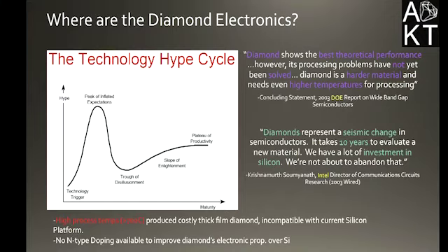Diamond is a harder material and it needs even higher temperature for processing, meaning that diamond had to be deposited at over 700 degrees Celsius, which, incorporating that with silicon electronics, would fry the underlying circuitry. So we turned to the biggest market user of silicon, Intel, to see what their opinion would be, because obviously they have the biggest stake in semiconductors.